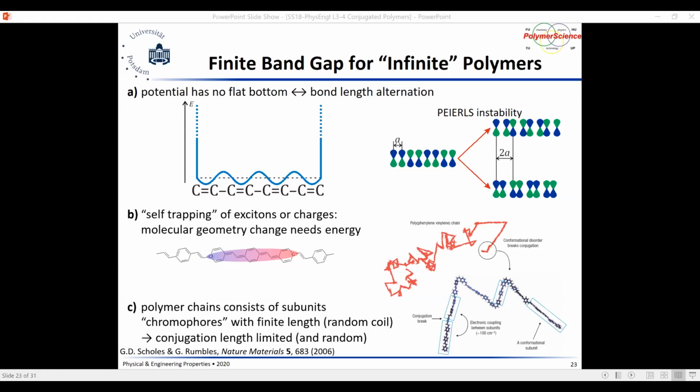From this, we can see that the electronic and optical properties, including energy and delocalization of the excited state, energetic dispersion, and electronic conductivity, all depend on chain conformation. And this can be tuned as simply as through the choice of solvents, or the way we dissolve the polymer to make a solution, and thereafter to make a solid state, and so on.